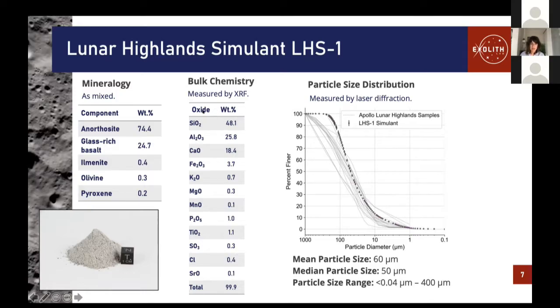So here's the bulk chemistry. This bulk chemistry table is not something that we aim for. This is just what we get from the mineralogy, and it's reasonably close to lunar samples. And then here's a plot of the particle size distribution. The bigger, darker points here are the particle size distribution for the simulant, and the curves in the background are the representative Apollo Highlands samples. So at least from the 100 micron size on down, it's a reasonable match.